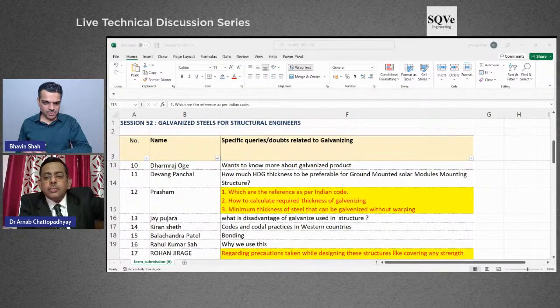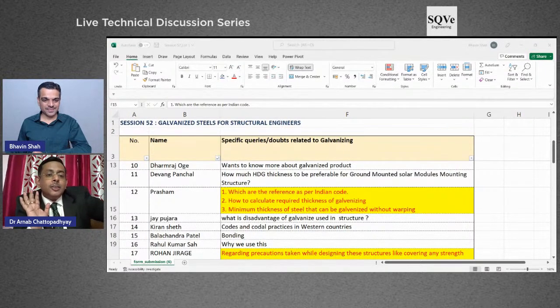The minimum thickness of steel that can be galvanized. For continuous galvanizing, I have seen 0.12 millimeter. Because sometimes thin sheets for your roofing application, dooring application in automotive, 0.1 millimeter galvanized steel also can be galvanized. So thickness has no problem. But you cannot do in the batch galvanizing because it is not economically viable. But in continuous galvanizing, many steel plants are producing 0.1, 0.2 day and day out.